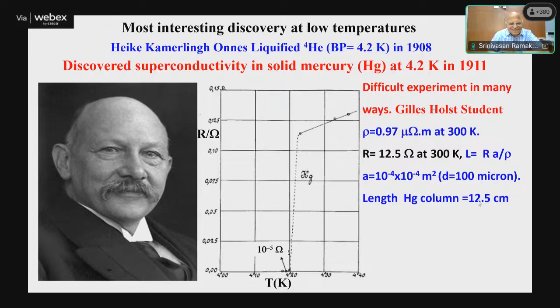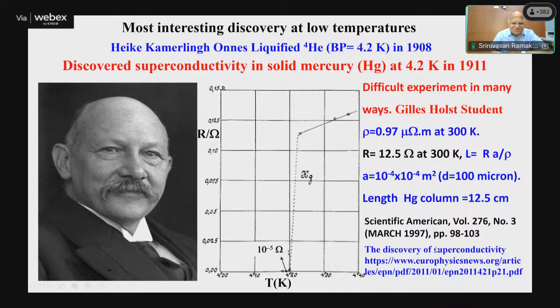How do you do that? You put it in a narrow capillary, and it so happened that the capillary height is about 12.5 centimeters. You want to perform resistivity measurements on this so that you can have a measurable resistance before it goes to a superconducting state. So it's a very tough experiment in 1911. Holst, driven by Kamerlingh Onnes, was able to measure it. They showed a sharp transition at 4.2 K, which became the superconductivity of mercury. And there are some interesting accounts which I have given here, which are in this article.